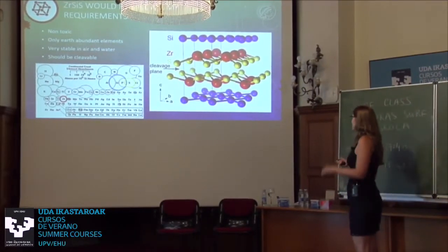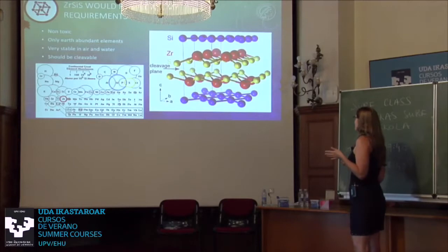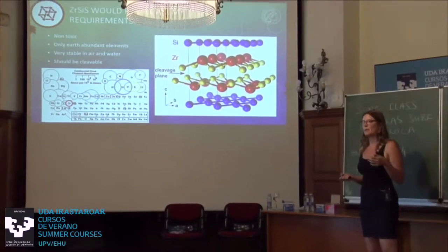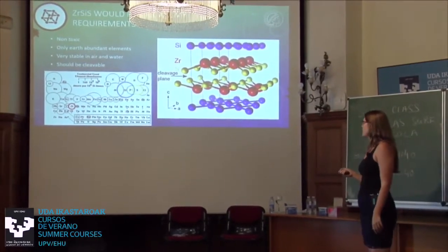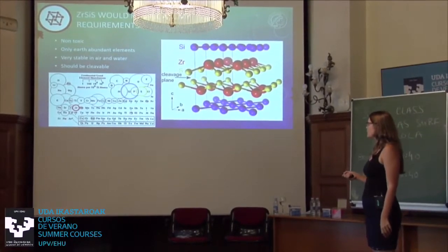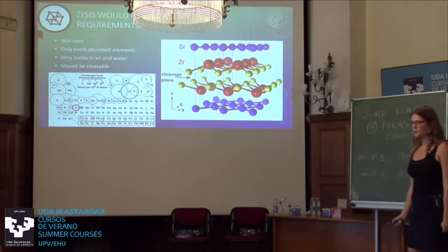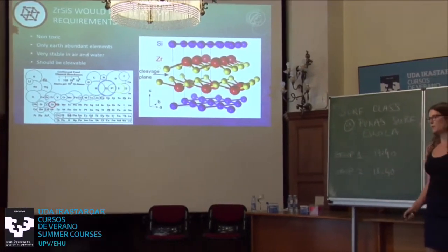You can cleave it. It's a layered structure, and this is crystallizing in space group 129. What I also liked is it's really only made out of cheap and non-toxic elements, and the powder was reported to be stable in air, water, and even diluted acids.